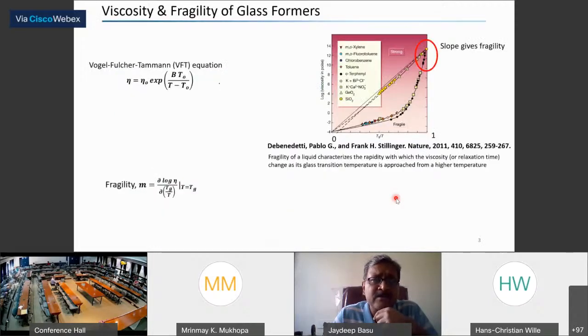Basically, the two terms we used in the title, viscosity and fragility, I think at least the viscosity is definitely well known to the audience. So this is a very well known plot, typical of glass formers, looking at the viscosity as a function of temperature or inverse temperature scaled to Tg. To cut a long story short, there are different materials, and we work with one such glass former, which is a polymer. On this log plot of 1/T, some materials show this kind of linear behavior, which is called strong. For example, silica is one such example, but there are a lot of other materials which show this fragile behavior. That means they have something called fragility, and you can see this kind of highly nonlinear curve in this expression.